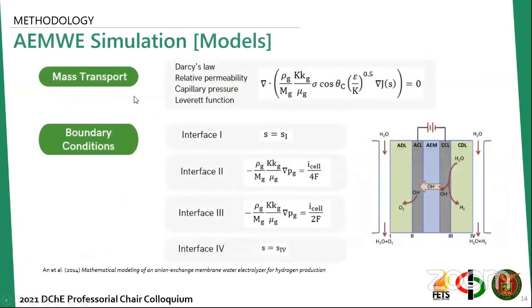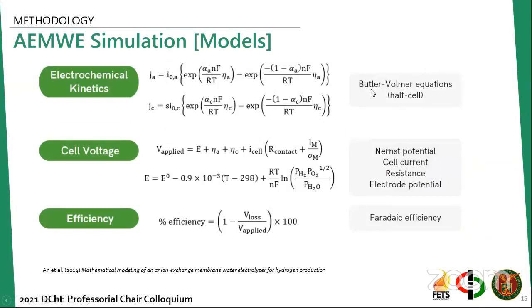For the models to be used for the simulation, we consider the mass transport equation for gases. In setting the boundary conditions, we take note that for interfaces 1 and 4, the liquid saturations are set to be equal. And for interfaces 2 and 3, we consider the oxygen and hydrogen evolution respectively. Electrochemical kinetics will be described by the Butler-Volmer equations in the anode and the cathode electrodes. For the cell voltage, we calculate the applied voltage through the sum of the resistances, including the Nernst potential. And for the Faradaic efficiency, we relate that with the voltage loss and the voltage applied from the equation above.